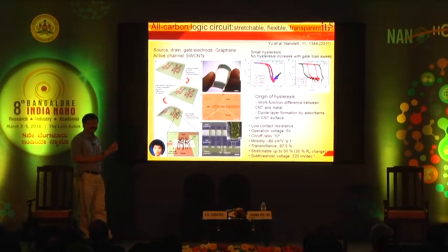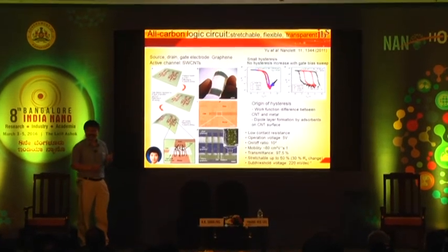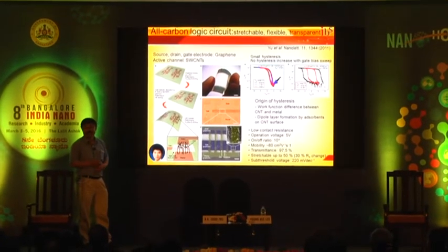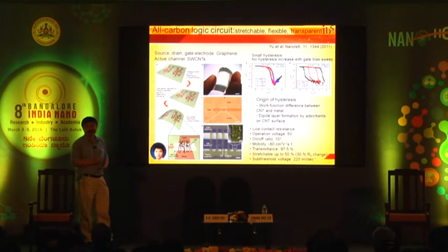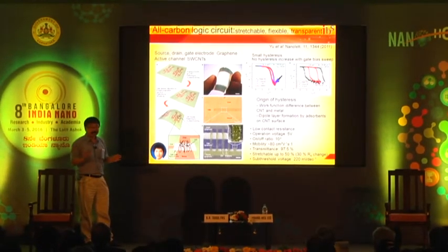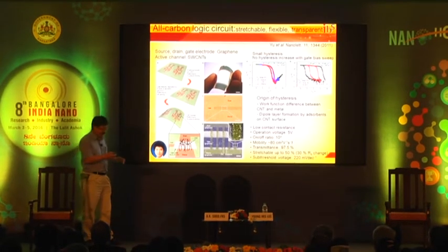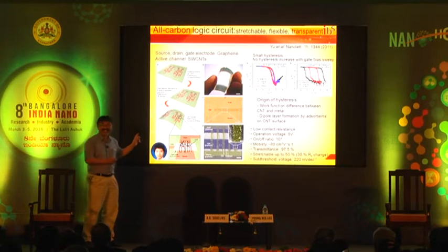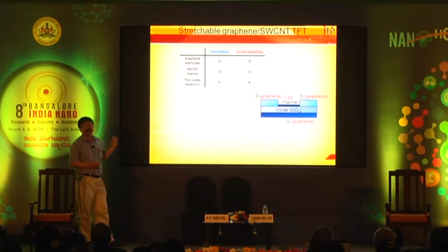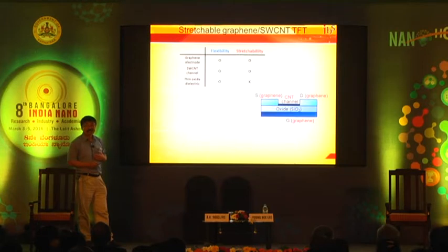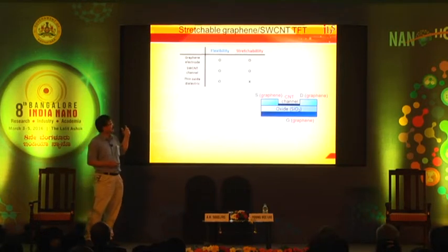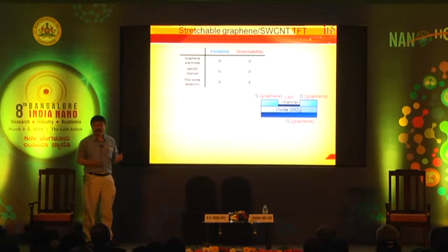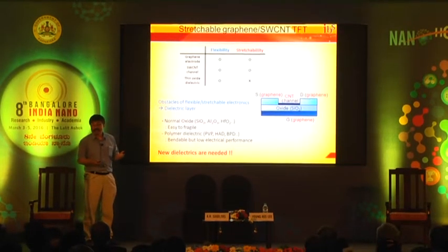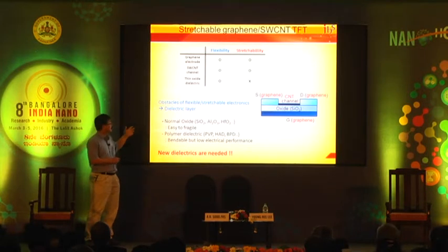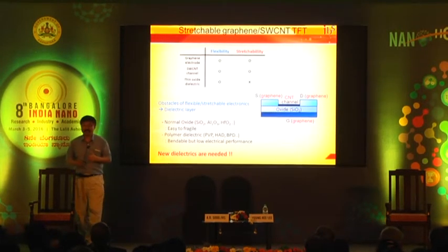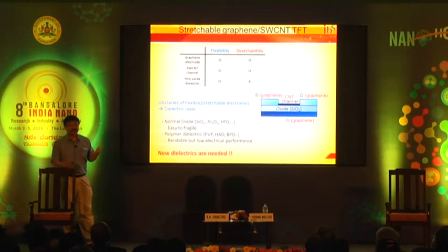Still, I didn't mention this back gate oxide, which is still a silicon oxide. In our laboratory we usually use 300 nanometers, and it cannot be stretchable at all. So I had been cheating a little on this. So we thought about how we can play with this gate oxide. Of course, one can introduce some polymer. Polymer is an insulator, but most polymers show high leakage current. So for a highly sophisticated device, you cannot use it.